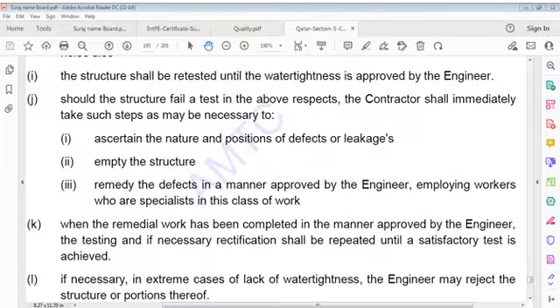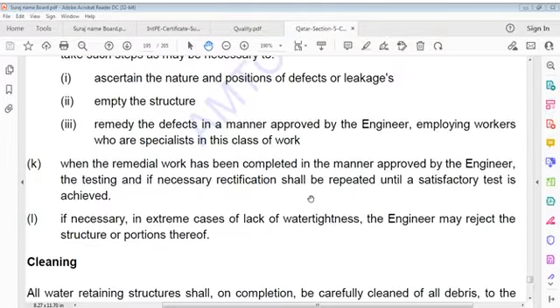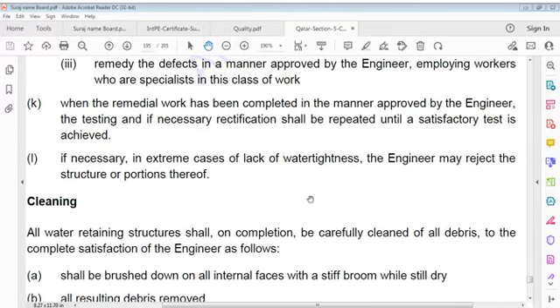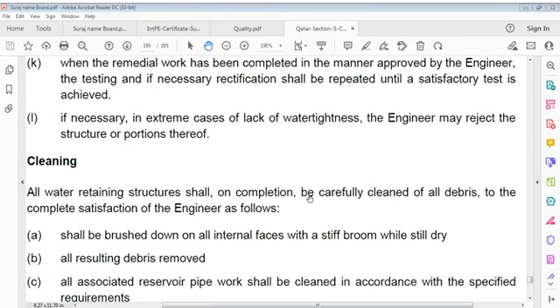When remedial work is completed in a manner approved by the engineer, testing and if necessary rectification shall be repeated until a satisfactory test is achieved. Be clear, even after remedial action, you have to test again. If there is another leakage, you have to do it again and again until you get a satisfactory test. In extreme cases of lack of water tightness, the engineer may reject the structure or portions thereof. Very serious matter. If it is not found watertight, the engineer will reject it or part of it. Do it again.